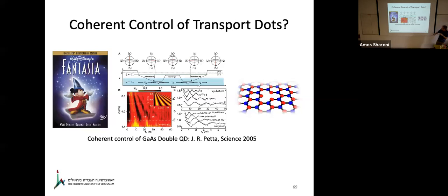This is Jason Petta, still from his postdoc with Charlie Marcus. The same toolbox people applied for gallium arsenide dots or nanowire dots. Can you do this with atomic dots? The benefits are huge because you have a quantum sensor, which is atomic in dimensions, 1 nanometer away from the system. It's very sensitive, very close. I don't know if it's possible, but it would be nice to try. And that's it.